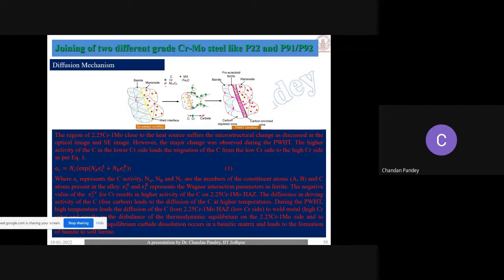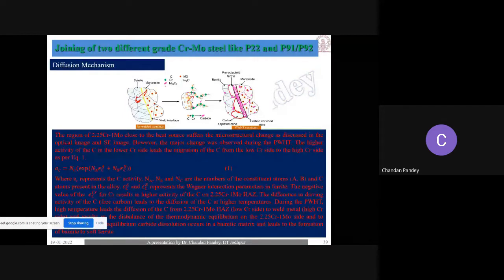Here there is a presence of the carbon element, a small amount of carbon. So during the process of heat treatment, we get the diffusion of that carbon from here to here along the boundary. And due to the diffusion of the carbon, here we get the formation of the soft zone. It is depleted of carbon, and that region is called the pro-eutectoid ferrite region.